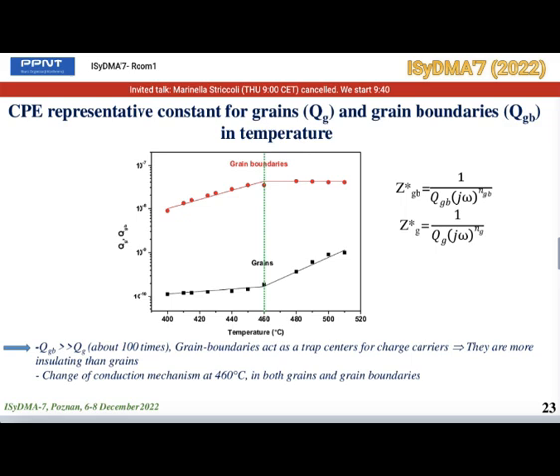In the equivalent circuit model, a constant phase element for grain boundaries has been inserted instead of a capacitor, due to non-ideal behavior of capacitance. We have also plotted the constant phase elements representative for grains QG and grain boundaries QGB versus temperature. We notice that QGB is about 100 times higher than QG. Indeed, the grain boundaries act as trap centers for charge carriers, so they are more insulating than grains.